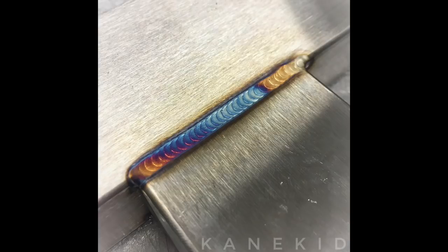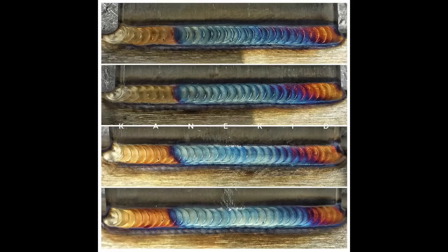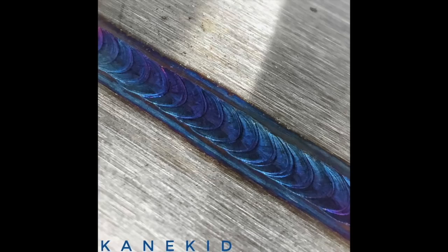Yeah. A lot of what I focus on is welding preparation. In order to get the weld that I want, usually it's about 90 to 95% weld prep, and the other 5% is welding, and at that point the welding is the easy part. Anything other than an acetone wipe? What's a typical cleaning procedure for, let's say, aluminum jobs that you do versus stainless?